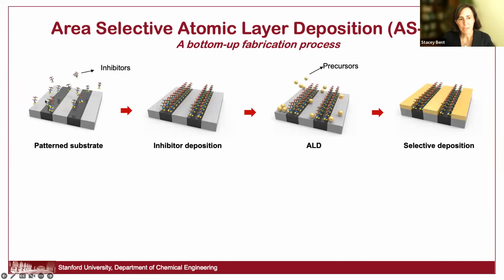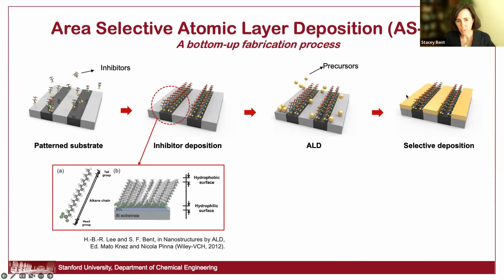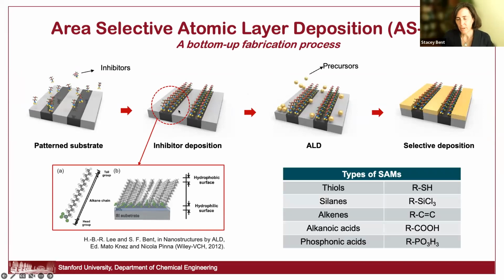So again, this is the process. You have some pattern, you expose it to inhibitors. They naturally go down on the non-growth region. Then you do the ALD process and you get growth only on the growth regions. The most common type of inhibitor to date has been these self-assembled monolayers, which have head groups of the type shown here and tail groups that are good at blocking access by these ALD precursors down to the surface.